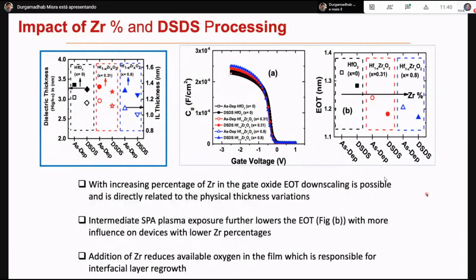So the film thickness, both the interfacial thickness, that is whatever we had this in these devices, we have an interfacial oxide. That device thickness went down compared to this is hafnium oxide, and this is hafnium zirconium oxide, 80% zirconium oxide. In all cases, when you expose the plasma, the densification of the film, both the dielectric thickness went down because higher densification, as well as the interfacial thickness also went down. These are actually physical measurement. Now, when you look at the CV, because of this, also the EOT, actually there is a significant improvement of EOT. That's because the dielectric constant, once the dielectric constant of the dielectric goes up, then EOT comes down for the same one.